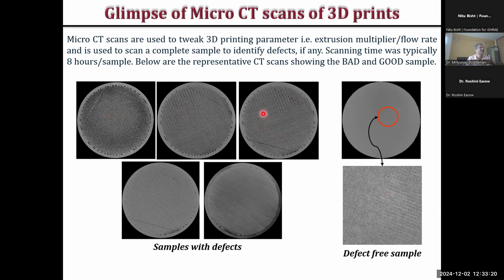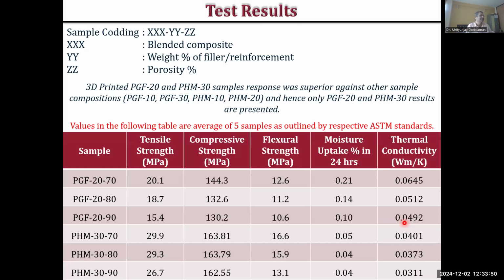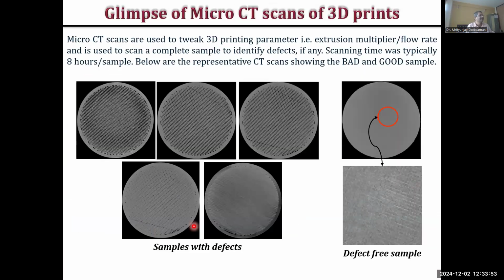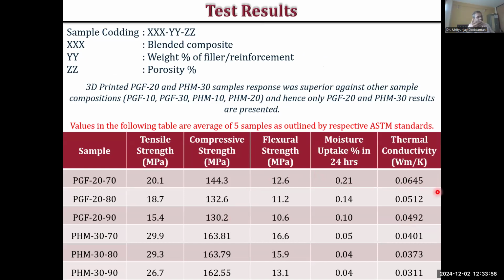So why these are with defect, you can just see there are some pockets here. But many times, let us say you need more damping, we introduce these pockets intentionally, which is not possible with every material system. So it depends on the application. But for this application, I was avoiding these pockets. And this is where we get a completely foamed, perfect sample, which can now go ahead with the Kelvin structure.